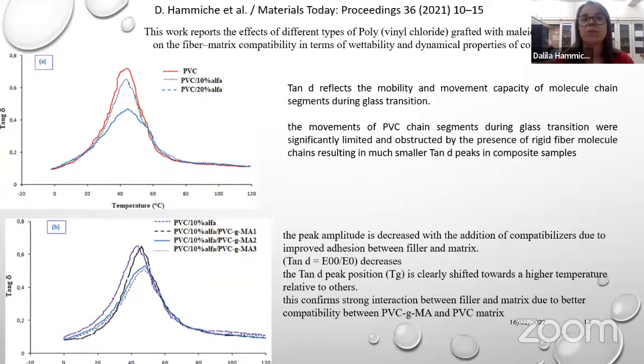It is clear that the movement of PVC chain segments during glass transition was significantly limited and obstructed by the presence of rigid fiber molecular chains, because generally vegetable fibers are rigid, and they can increase the rigidity of materials, resulting in much smaller tangent delta peaks in composite samples. And also, as we can see in this figure, the peak amplitude is decreased with the addition of compatibilizers. When we add the compatibilizer or the coupling agent, the peak amplitude is decreased.